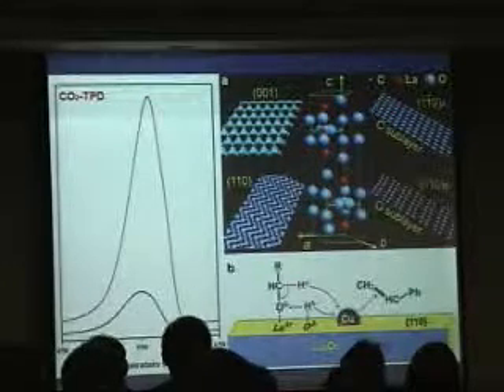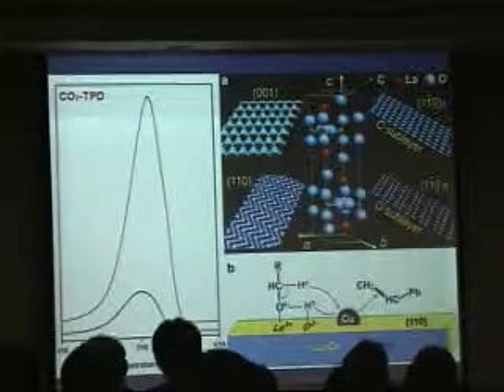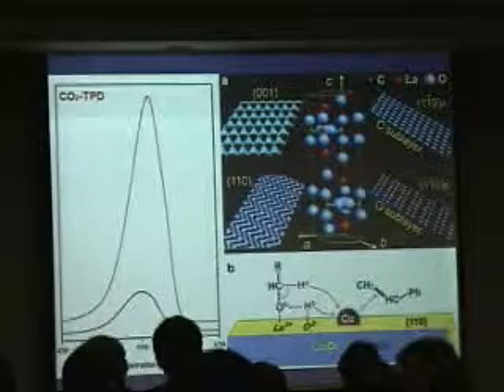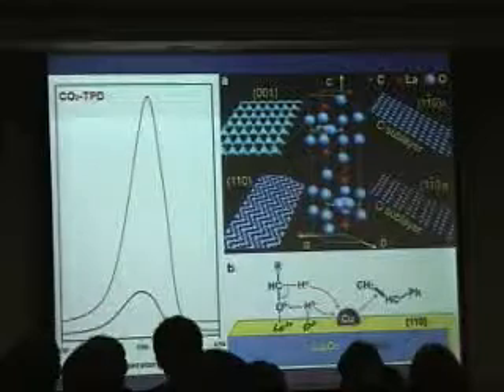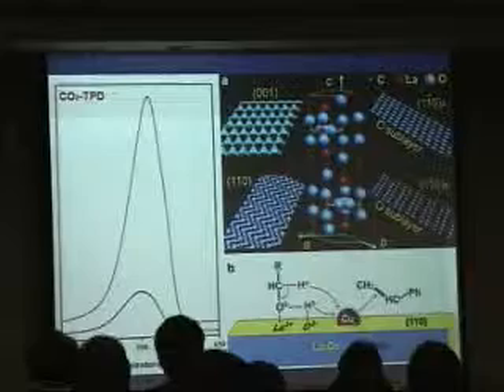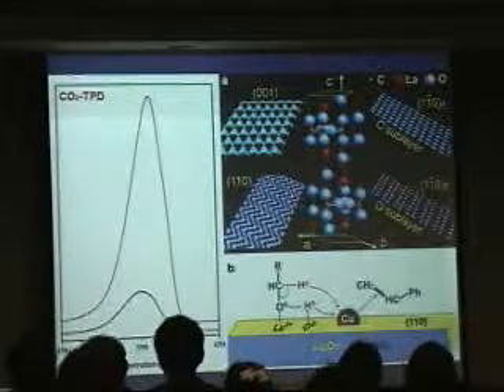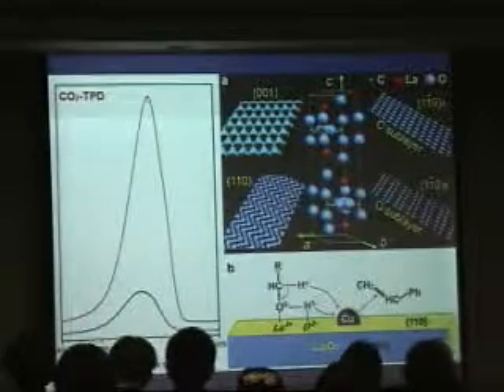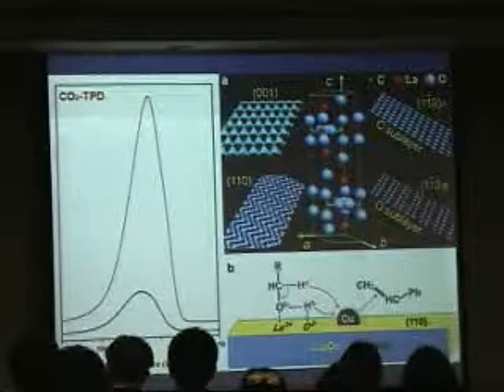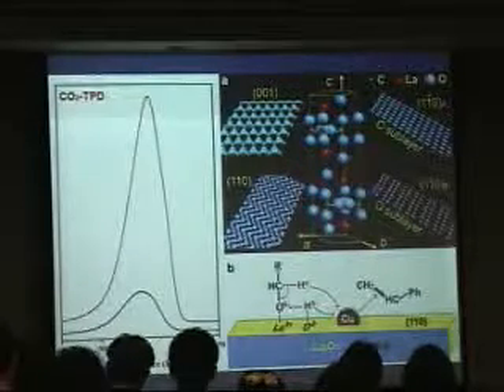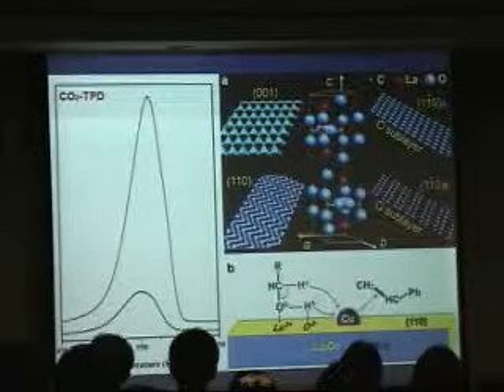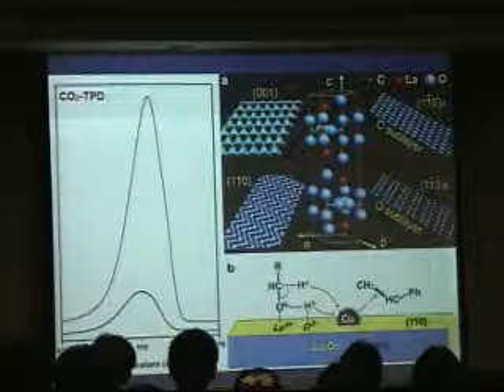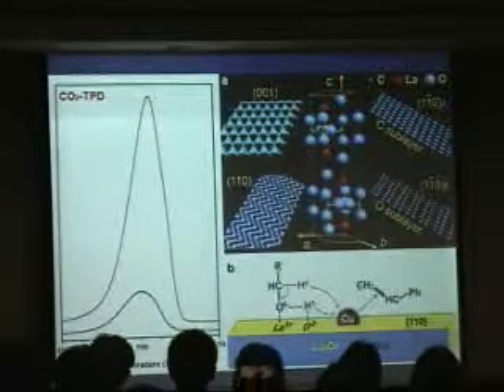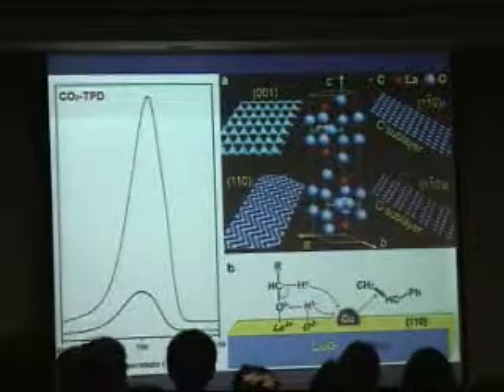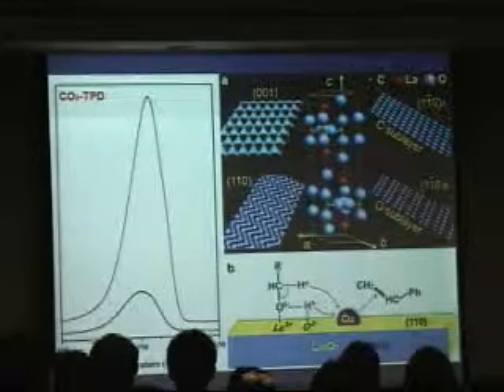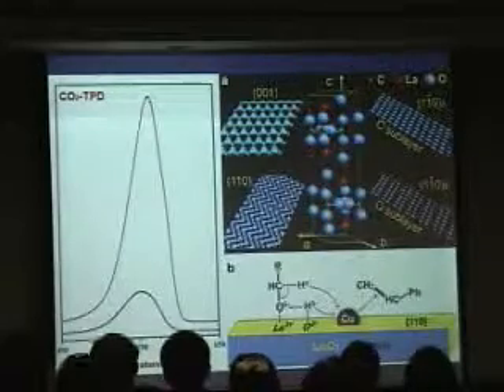On this surface, you can find the coordination like this, and the basicity of this support is much larger than the conventional lanthanum oxide. This is the conventional lanthanum oxide. We measured the basicity. This is medium strength basicity, not weak. Also, we don't want strong. This is very useful. Basic sites are very useful for alcohol activation. So you can find the shape has increased the basicity of these materials. And this basicity not only participates in the reaction to activate the substrate alcohol, but also provides some space for the deposition of copper particles. And the cooperation of the copper particles and the surface basicity promoted this reaction very efficiently. That's why we get a high yield of the aldehyde for the alcohol conversion process.